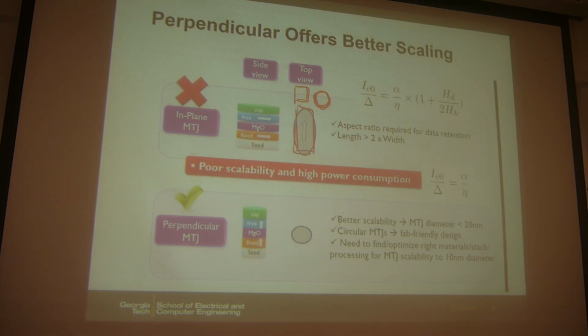The reason is that you want to introduce this geometry effect to this structure to help the magnetic orientation, in this case pointing up from the top view. If it's square, then it is easy to change the orientation because it does not have preference from the center. If it's symmetric everywhere, then this arrow may point into any location. Not good for the data retention.